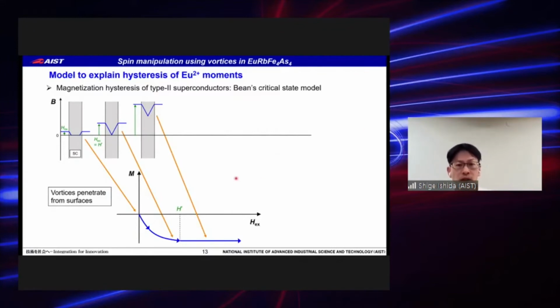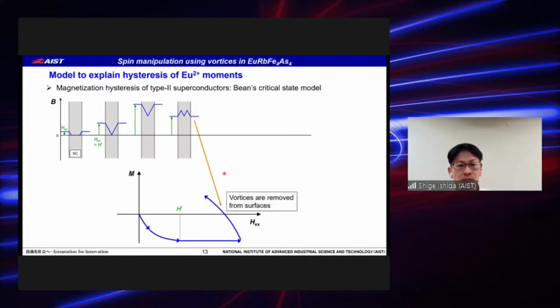Then when the magnetic field is decreased, the vortices are removed from the sample surface without changing the B profile around the center of the sample. During this process, the field inside the sample gets larger than the external field, so the magnetization becomes positive. With further decreasing field, the B profile is completely turned over.